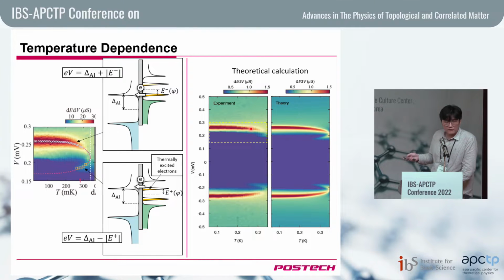This is just the temperature dependence. So as we increase the temperature close to the Tc of the ohmic contact aluminum, the Andreev bound state disappears as expected. And on top of that, near the Tc, an additional peak appears, which comes from the originally empty state of the upper Andreev bound state. But at high enough temperature, the upper Andreev bound state will also be partially filled due to thermal excitation, and we are seeing it at high enough temperature.